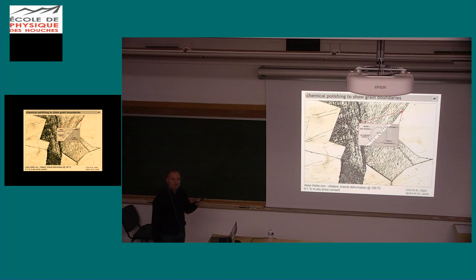And then the big trick is to clean these surfaces, and we got from crystallography a technique to use hexane, which is a completely non-polar fluid, to wipe the solution off the surface. They are using this to image crystal growth spirals, for example.